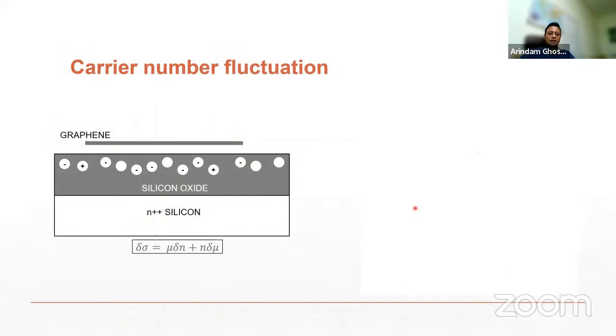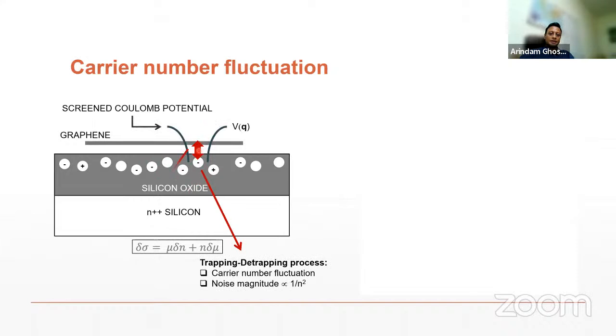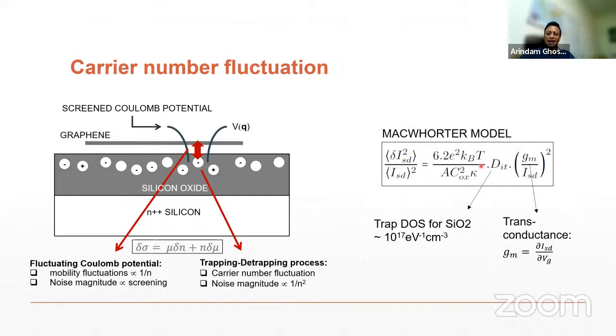The noise typically comes from fluctuations in the number of charge carriers and mobility. For example, there are a lot of traps in the oxide that the graphene is sitting on. So what happens is that if there is an electron which jumps out of graphene and goes into one of these traps, then it imparts a Coulomb potential back on the charge in the graphene layer. And not only does the charge number change, and that leads to change in resistance, but also the scattering changes, and that also leads to additional noise. And there are models, the McWhorter model is one of them, to calculate what the noise magnitude is as a function of electron density in the graphene layer. But it strongly depends, as you can see here, on the number of such trap states inside the silicon oxide layer that the graphene is sitting on.